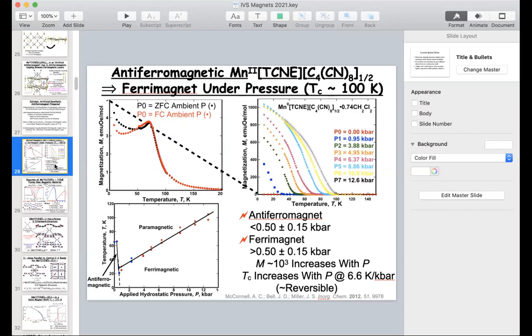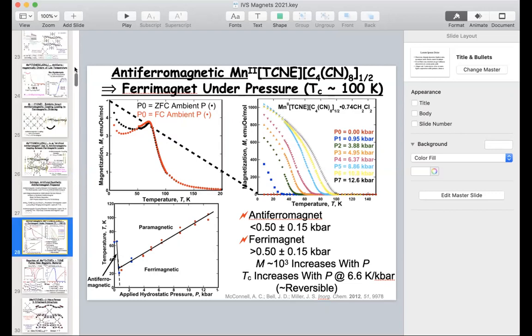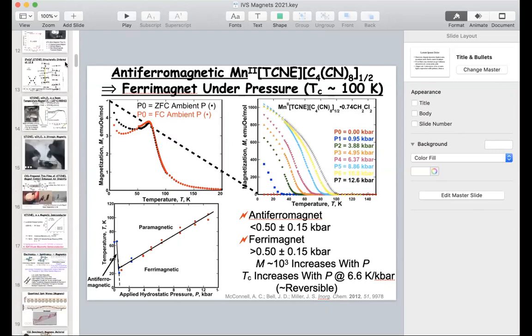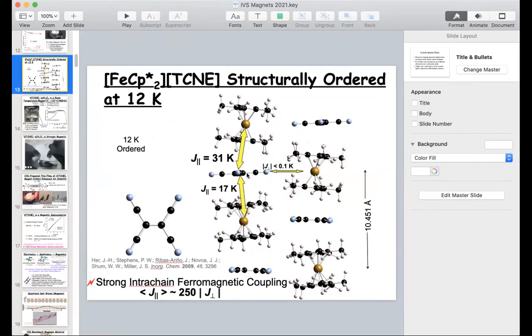I'm unaware of anything too, because now you've got to predict the onset of three-dimensional ordering based on a structure, and we never have enough structural information. It's very rare we have ordering temperature, structure below the ordering temperature, and enough information. I mean, there's so many couplings going on that are competing. Generally, some are antiferromagnetic, some are, I didn't show this, I rushed through here. But the coupling for the TCNE decamethylferrocene is strongly coupling within the chain and some weak antiferromagnetic coupling between the chains. And the net coupling is ferromagnetic and it magnetically orders at 4.8 Kelvin.